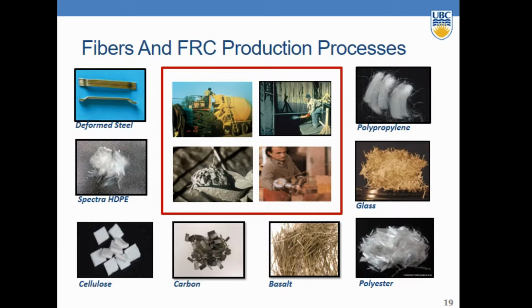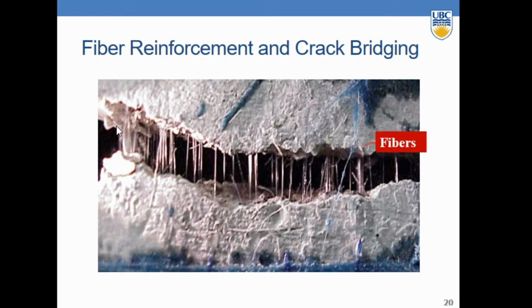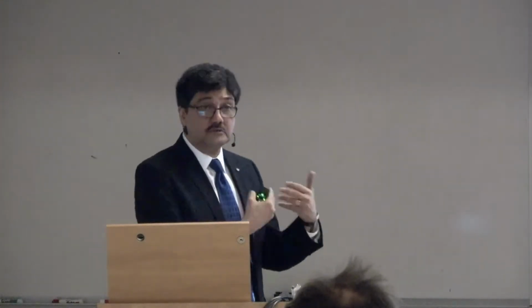So FRC, fiber-reinforced concrete, is where you take the concrete and add fiber to it. This is the concrete which we spray, and we can add these fibers of different types of materials. I will talk a little bit about the cellulose particularly that we're using in order to produce concrete which has much better characteristics. Concrete with fibers would look something like this, and what you'll notice is that the fibers become wonderful bridges. If the concrete cracks, the fibers, which could be cellulose, are bridging the crack. The moment the crack bridging takes place, you don't allow these deleterious agents to go inside the body of the concrete, and that makes the concrete much more durable.